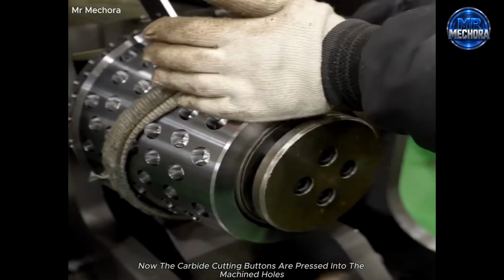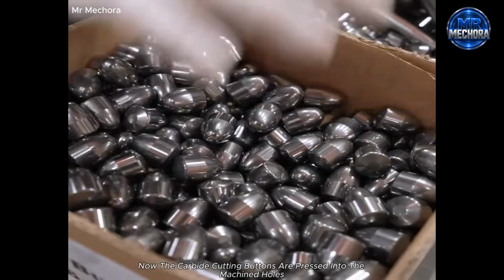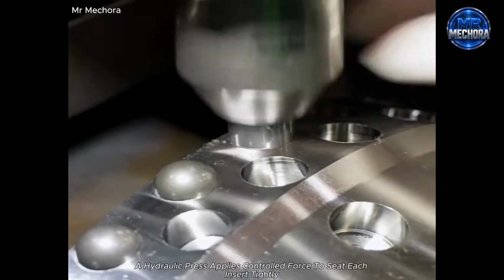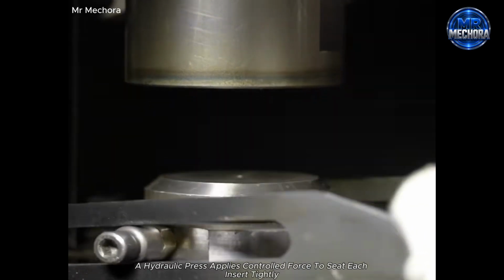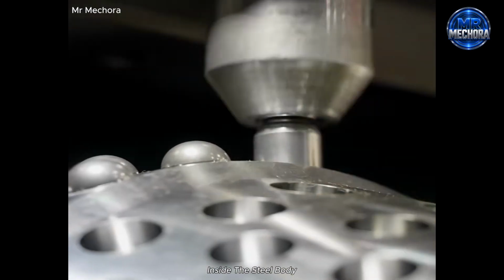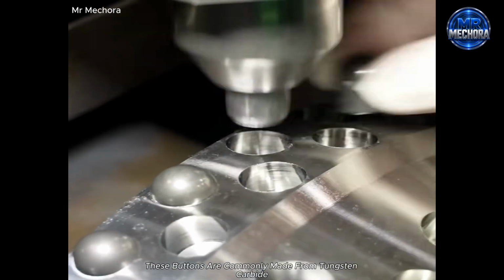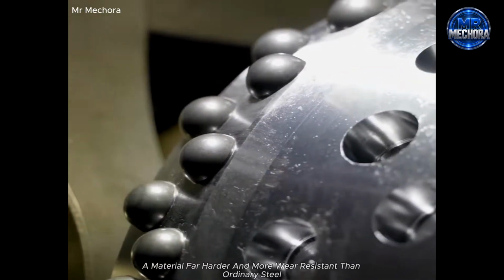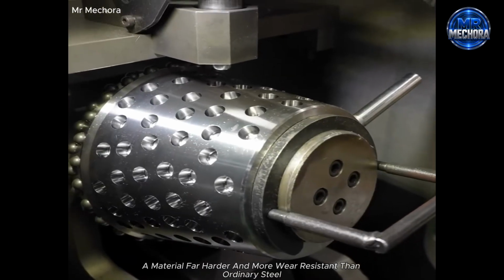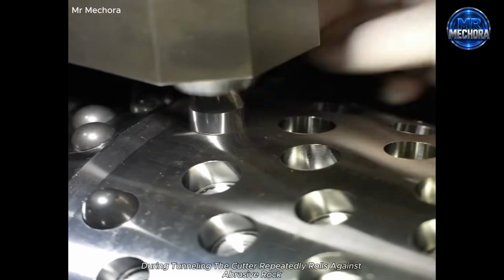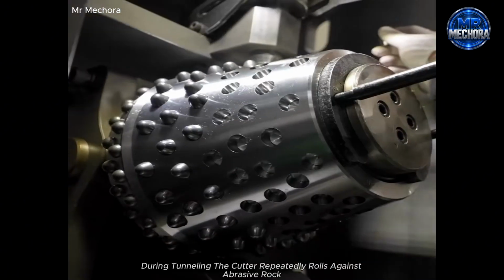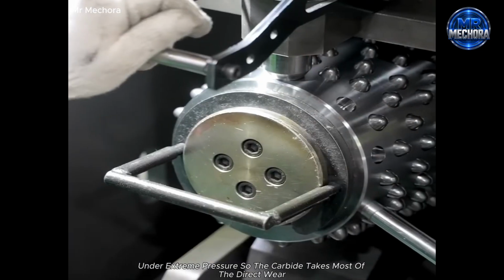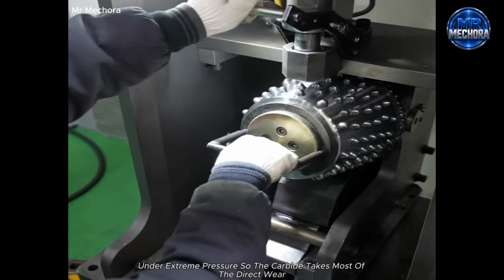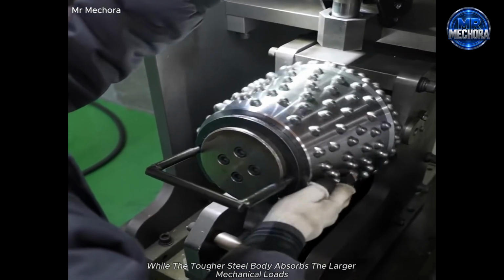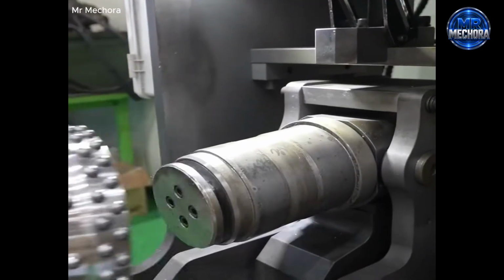Now the carbide cutting buttons are pressed into the machined holes. A hydraulic press applies controlled force to seat each insert tightly inside the steel body. These buttons are commonly made from tungsten-carbide, a material far harder and more wear-resistant than ordinary steel. During tunneling, the cutter repeatedly rolls against abrasive rock under extreme pressure, so the carbide takes most of the direct wear, while the tougher steel body absorbs the larger mechanical loads.